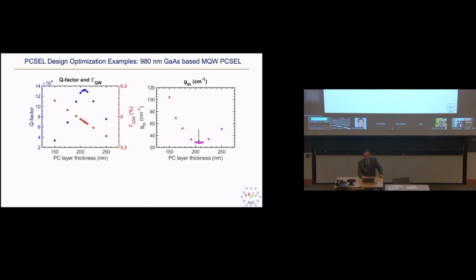And finally, we can predict the gain threshold. The gain threshold is basically the minimum material modal gain required for lasing. So low is better if you want to get a laser, right? Generally speaking, in this case, we look at the PC thickness and gain threshold relation. So we can optimize the thickness so that we get a low threshold.